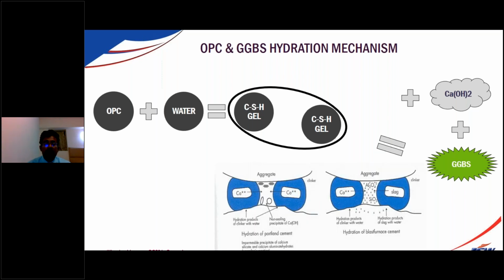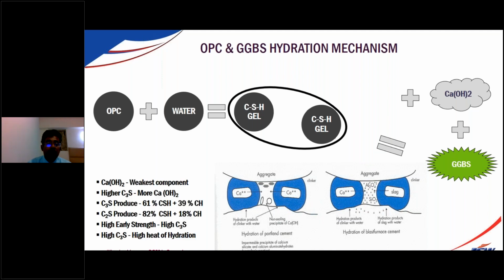So this is the diagram which shows that in pure Portland OPC cement, you have a non-sealing precipitate of calcium hydroxide. When we use GGBS, the slag will react and create a beautiful product, the hydration product of slag along with water. That is the beauty of the product.